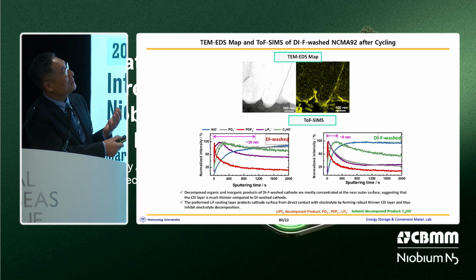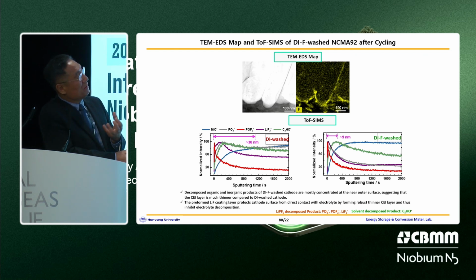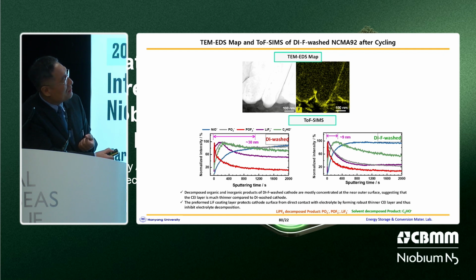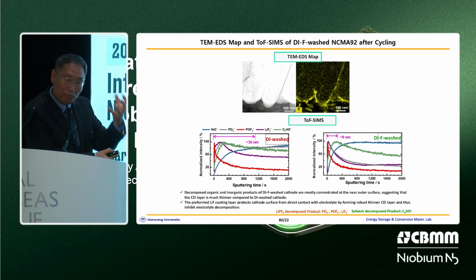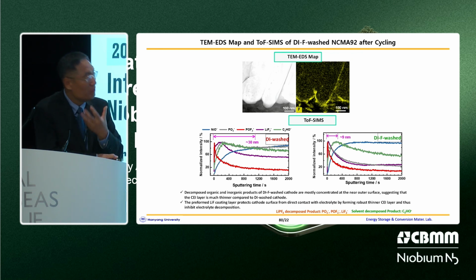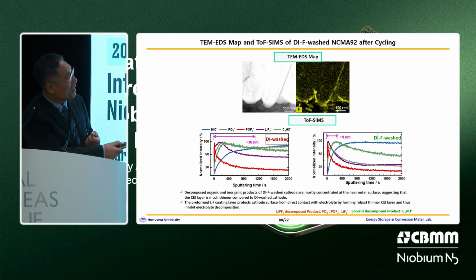And this is a TEM and ToF-SIMS image after long-term cycling. After long-term cycling, we can still observe a fluorine-rich layer both on the particle outer surface and in the grain boundaries. And also, as you can see here, we can observe the PO2, POF2, and LiF2 negative ions from the ToF-SIMS image due to the decomposition products of the lithium salt. We also observe the C2HO negative ion, which is the solvent decomposition product. As you can see, this is the DI-washed, and this is the DIF-washed cathode. This is the CEI layer.